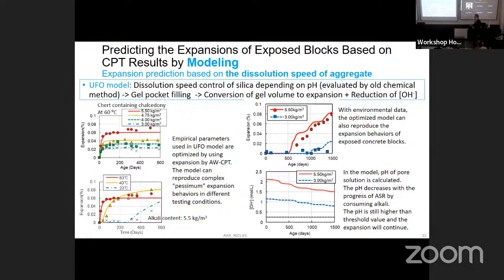First, think about the dissolution speed determined by chemical methods. Then this generated ASR gel first fills some spaces in the rock. Then this gel should be converted to some expansion. And this reaction results in the reduction of hydroxide concentration. Of course, with this kind of model, we need to fit some parameters. But by fitting some parameters, this model can reproduce complicated behavior like this.